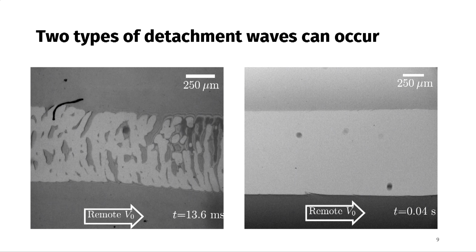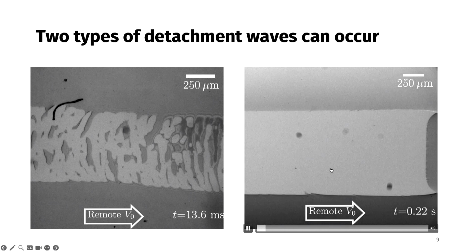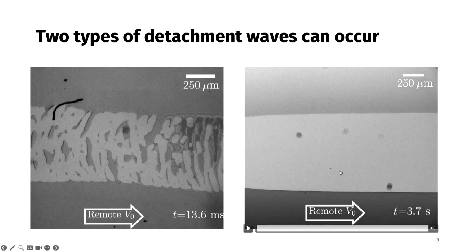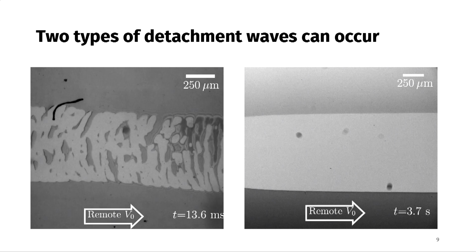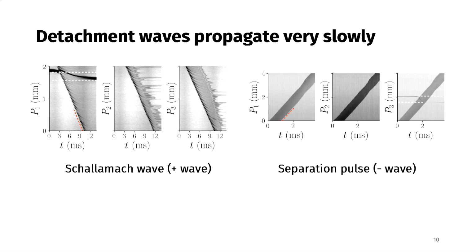But if you change that and do the same experiment, you will see something very different. Again, you slide in the same direction, but now you see a wave go in the opposite direction, right? And just keep your eyes peeled on this point, which is initially here, now it moves here. So the point is moving in the direction you're moving the body in, but the wave is going the other way, okay? And there are two distinct types of waves. The features are different, the wave speeds are a little different, and so on. Now, the key message that I'd like to get across here is that for the two waves, you can construct what are called space-time diagrams.